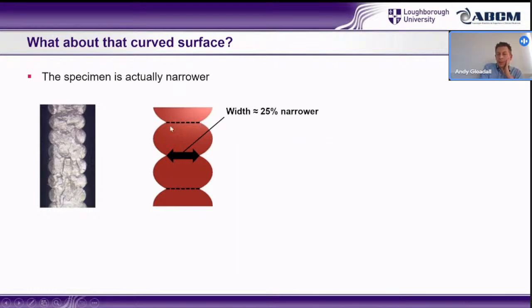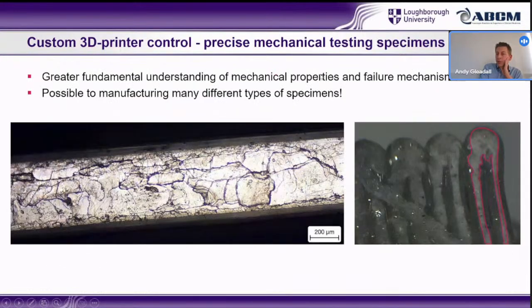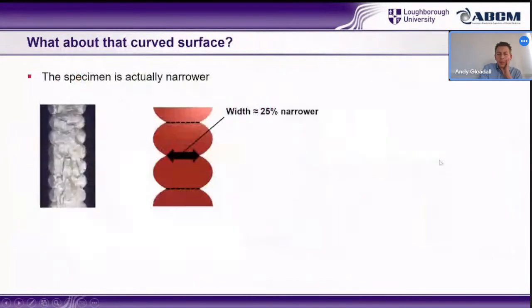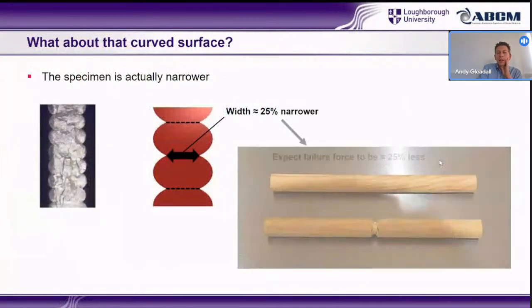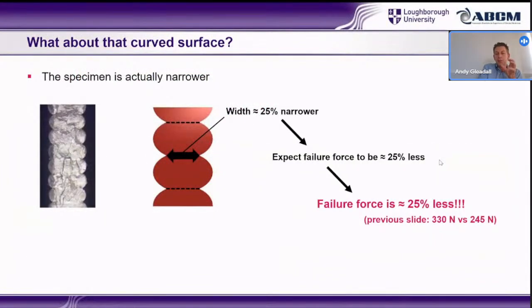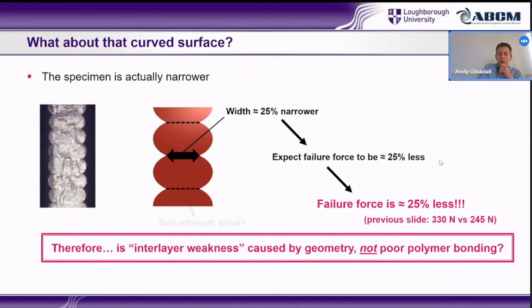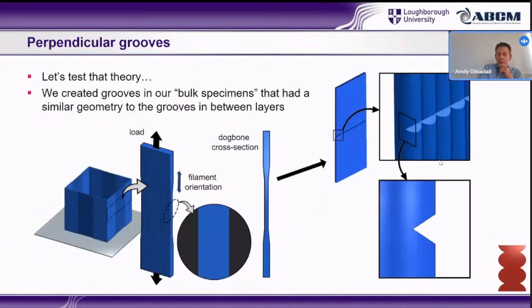But that's quite a challenge to do on a geometry like this. So by simplifying it and really analyzing the micro scale geometry, we could find that actually it doesn't seem like the interlayer properties are any worse than the bulk polymer.